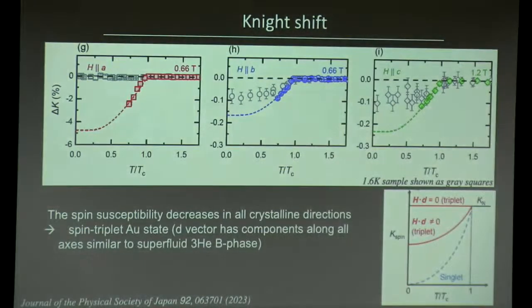Okay, so now let me show you evidence for the triplet nature of superconductivity. Essentially, there's Knight shift data, and for a singlet superconductor, if you go below the superconducting transition temperature, you see a huge change in the Knight shift. Whereas for a triplet superconductor, depending upon the direction of the magnetic field with respect to the D vector, you'll either see no change or a very small change.